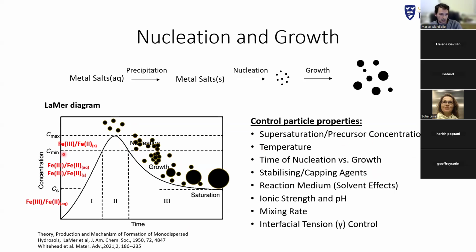So supersaturation is the concentration that you have here. You can tune this by temperature. If you have a high temperature, you might induce more growth. A low temperature would induce more nucleation.